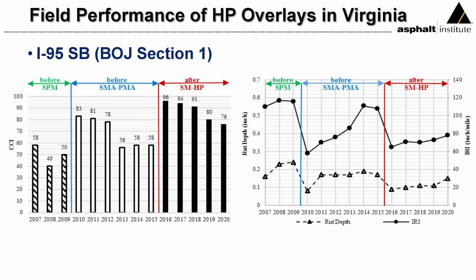On this particular slide, we have rut depth and what is their critical condition index. Okay, so you'll notice that it's not shown on this slide, but 60 is kind of their critical condition, which would initiate some type of rehabilitation. In the state of Virginia, that's normally a mill and fill. So you'll notice as these values dive below 60 on that graph on the left, that's when you're seeing a new